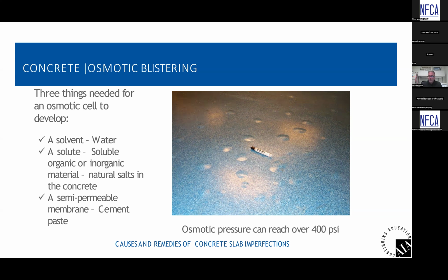So Seth, when you have a high pH or alkaline content at the surface, salts at the surface, those salts are basically drawing up the water. Yep. Water is attracted to salt because salts are desiccant, very, very dry. Absolutely, that's exactly right. So this is one of the reasons why we look to control through pH testing the level of salt. If you've got 14, you've got a very high pH level, then you've got potentially this problem coming. Is that how you see it? That's a possibility. I mean, if we have a high salt content at the surface, that's one component.